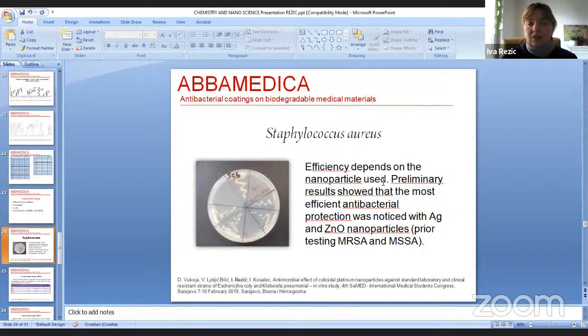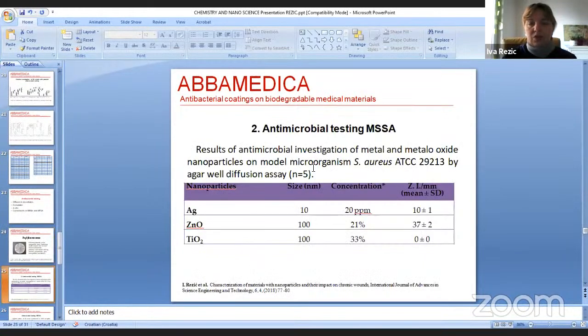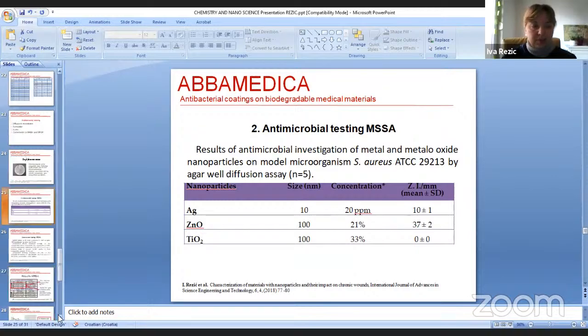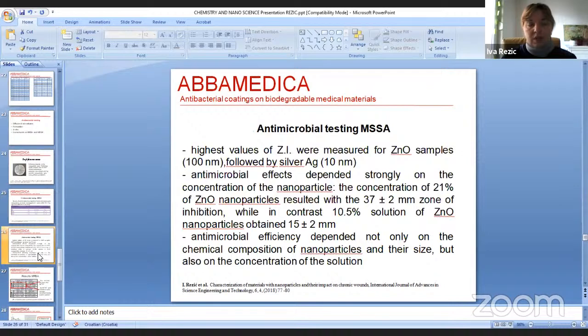And preliminary results on different Staphylococcus aureus that are not MRSA and MSSA have shown some effects, but then you have this table, the results really produced on MSSA and MRSA microorganisms. And you will see that we really have positive effects against these really problematic microorganisms. So what did we see during our experiments? We saw that this is the zone of inhibition. This is the area where microorganisms are actually dying due to the presence of nanoparticles. It really occurs on this, and it's really significant. And the best results we had were with zinc oxide nanoparticles, followed by silver nanoparticles.